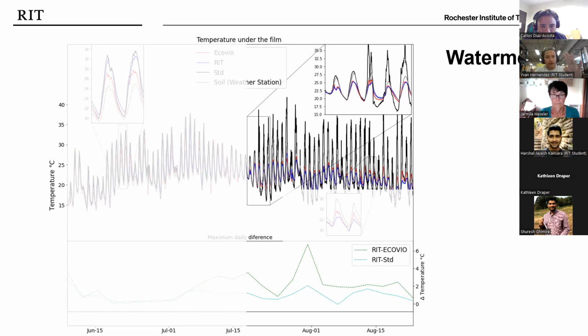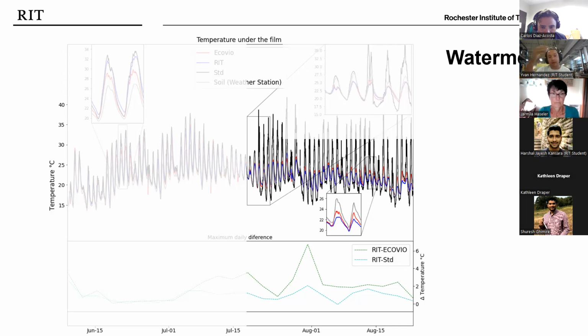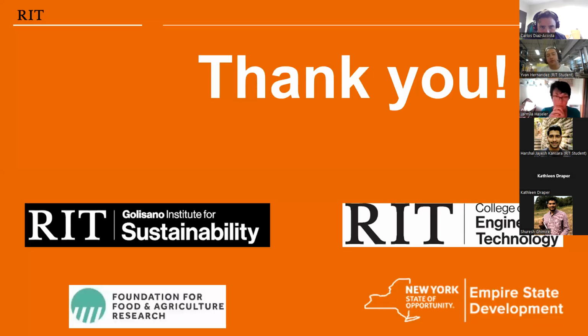So now we cannot trust that black line, but that is okay because that's the LDPE film and there's a lot of literature on it. But when we looked at the RIT film and the biodegradable one, they're very close to each other. So that means it's good. It looks like it's doing okay. It's doing its job. And we're just waiting until actually tomorrow we're gonna meet at the farm and pick up the rest of the harvest to be able to bring you the rest of the data. So finally, what can we say? We made a multi-layer agricultural mulch film that apparently until now it's performing equally as the others.